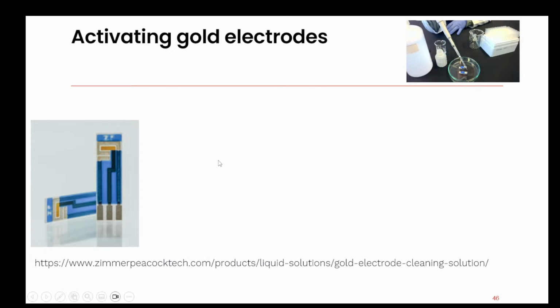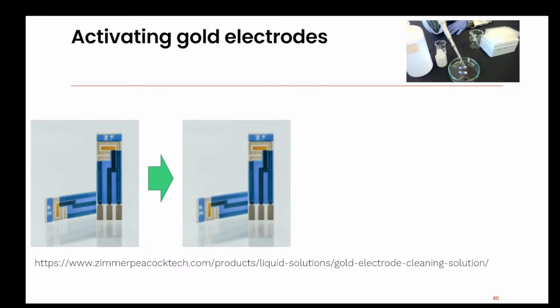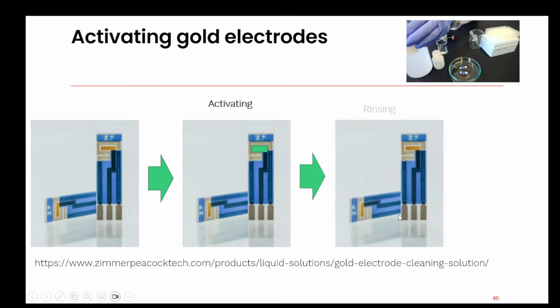We generally do this. So the next problem I suspect you've got is gold is really good at passivating. It's really good at adsorbing material from surfaces. So in fact, I have a video in this link. You have to watch that because you actually have to activate that gold before you really start the process. So we do an activation and we rinse it. Even if we've produced a screen printed gold electrode and they've passed our quality assurance, just before we start doing the functionalization, we activate them by essentially chemically cleaning them. I didn't see any mention of that in your notes. So we do a chemical cleaning step.